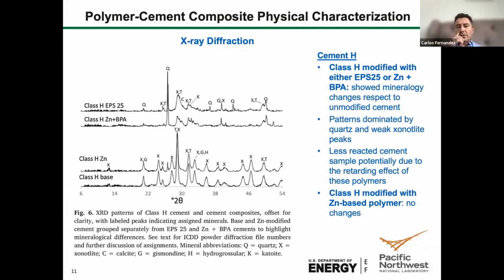After 24 hours, 48, or even after 5 days, you end up having all this diffraction pattern being the same as the control cement. But in the first 24 hours, there is some retardation, even after the first 3 hours that I showed you in the rheological properties, and you see some peaks, mainly weak xonotlite and quartz, so still unreacted pozzolanic material.